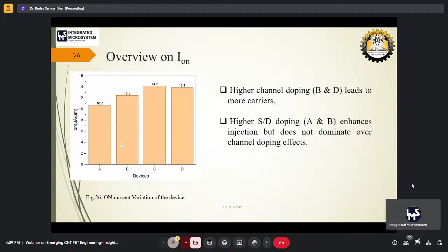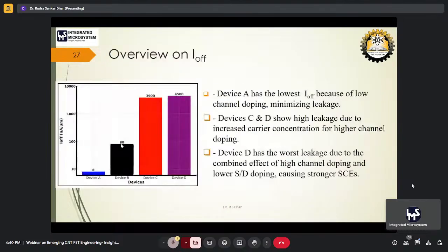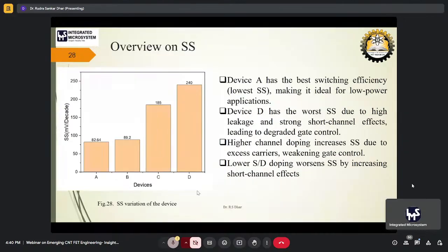We are getting an on current, Ion, and device C is giving a better Ion, 14.2, in comparison to A having 10.7. This is the Ioff for the different devices, which is quite good for device A, while C and D are not working well. So that is what we observed. Therefore, C and D are expected to have very high leakage. These things were expected, and that is what we were getting.